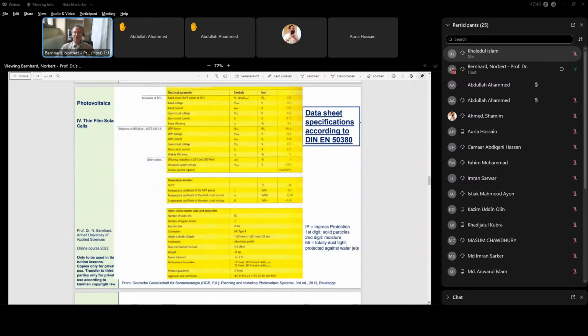Okay, this is a selection of the module parameters as they should appear. No, these are not a selection, these are precisely the module parameters as they should appear in the specifications according to German or European standards for the rating of the module. You see, it's the behavior at standard test conditions, but it's also the behavior at the nominal operating cell temperature. And for all these, the power has to be rated, the voltage, the current at the MPP, and then also the open circuit voltage, the short circuit current, and the efficiency. Okay, you see this example is obviously an older module because the efficiency here is, at least with respect to modern standards, moderate.